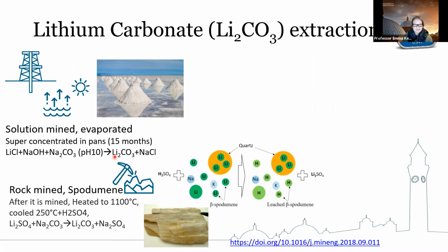The interesting thing for me when I was looking into the kind of the mining and the mineral extraction was that sodium carbonate is actually used in the manufacture of lithium carbonate, and then produces sodium chloride. So here the lithium chloride is mixed, it changes the pH, you add in the sodium carbonate and the lithium carbonate drops out of solution. On the other hand, lithium can also be mined from rock, and one of the main sources of lithium, for example, from Australia, is a rock called spodumene. This rock is first heated to form a beta spodumene, and then the lithium leached out of the rock. And again, interestingly, sodium carbonate is again used in the formation of the lithium carbonate within this system as well.